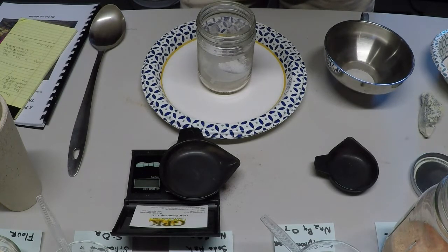So we may have a small amount of iron pyrite if we didn't get a complete roast, which I believe that we did, as well as I believe we got rid of all of the charcoal by ashing it and burning it off. Charcoal reduces lead oxide at a real high rate, 18 to 25 grams of lead oxide per gram of charcoal. So here's where we're at.